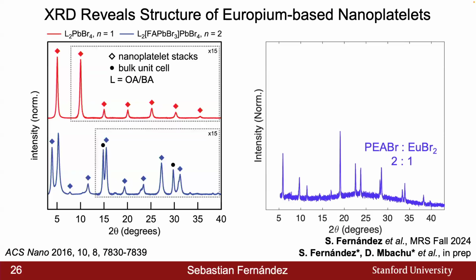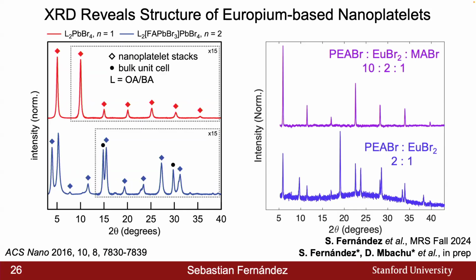When we centrifuged out our nanoplatelets and characterized them by XRD, we first see that this typical 2:1 ratio is not reminiscent of this 2D perovskite. Our hypothesis is that there is likely an underreaction between the phenethylammonium bromide and europium bromide precursors. But when we conduct XRD of the 10:2:1, which should in theory be the N=2 nanoplatelets, we start to see the periodic nature of the XRD scans, which are very reminiscent of the scan up here.